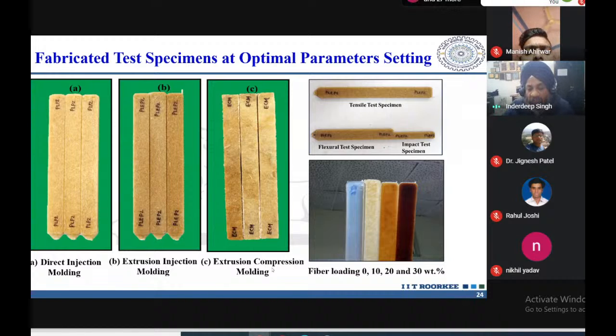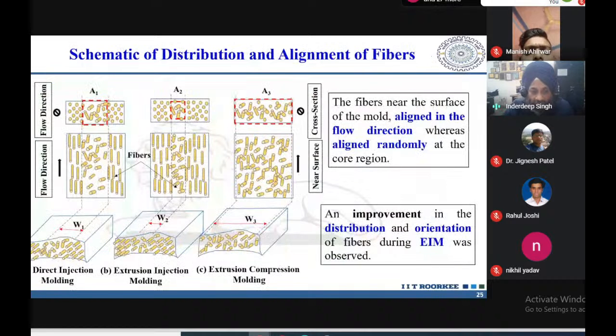So that also we have investigated and tried to explain using schematic diagrams like this, that once the fiber and the polymer melt flows in the mold cavity, how the fibers get aligned in a particular direction, and what is the fiber distribution and orientation in the core area, what is the fiber distribution and alignment at the surface of the composite developed. So the fibers near the surface of the mold are aligned in the flow direction, whereas they are aligned randomly at the core region. Now what can be the reason for this?